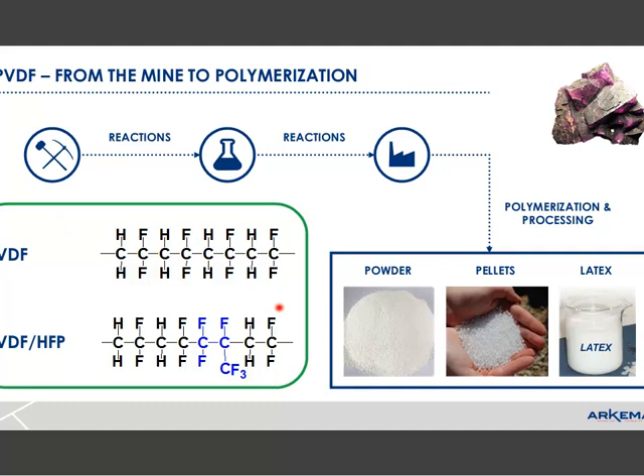PVDF resin is a very simple polymer. It's a linear carbon chain with alternating fluorine and hydrogen. Okay, and it's very highly crystalline, which lends itself to its good properties. There's a number of copolymers that can be used. CTFE is one. HFP is another. In this case, HFP is being used, which is hexafluoropropene. And the way it works is you have this fluorinated pendant group that is introduced. This pendant group interferes with crystallinity, making the product softer.